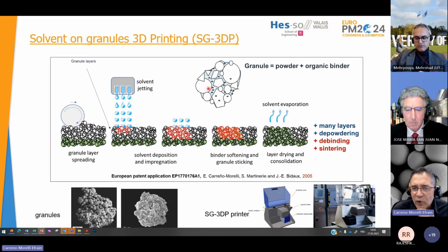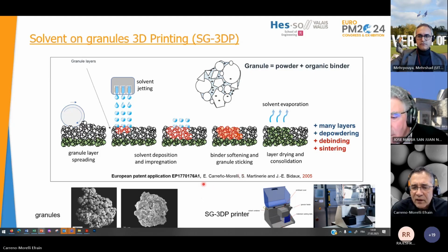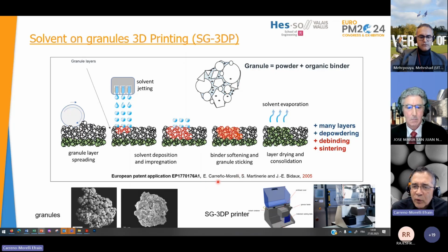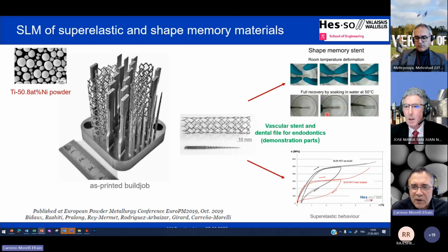Here you can put pre-alloyed nickel titanium powders, and also elementary nickel and titanium powder. We have also tested mixtures of nickel and titanium hydride powders, spherical nickel and angular titanium hydride. With these ideas, we even made a patent application many years ago, and it was at the origin of many other works. We have used this technique to process steel parts, soft ferromagnetic materials, and even hard metals such as tungsten carbide, cobalt. I won't present details of the preliminary results on nickel titanium. Maybe it will be later.